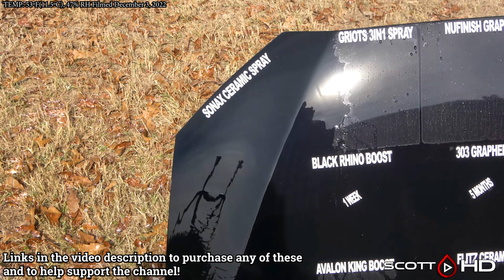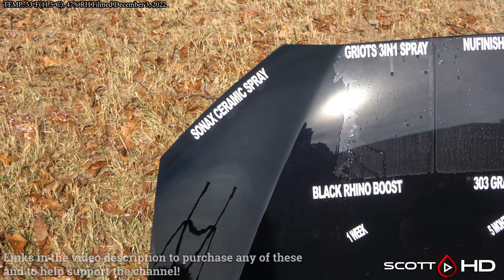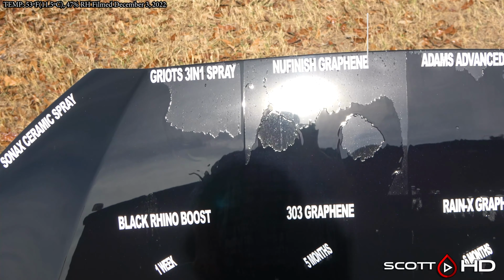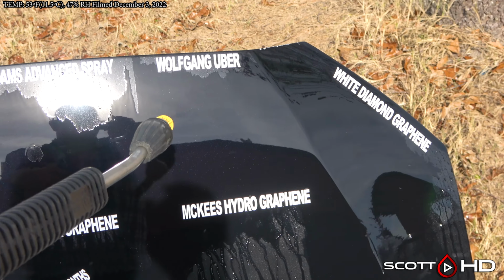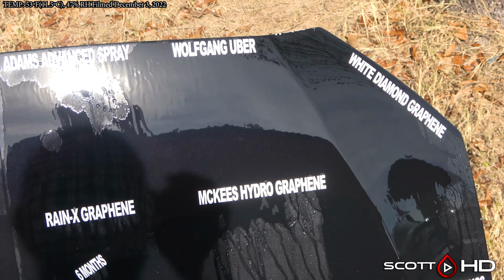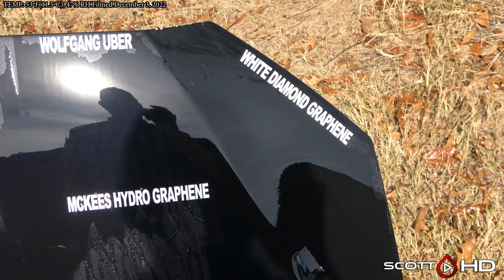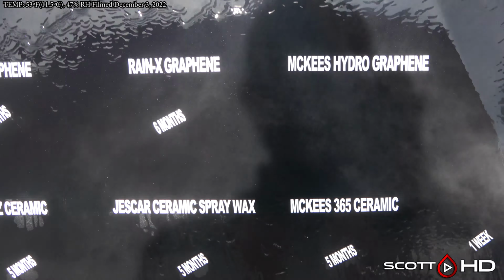So jumping right into it, Sonax ceramic spray, very close to failing. You can see that it sticks for quite a while. Griot's 3-in-1, got some wear on it. Nu Finish graphene, holding up pretty well, but again, it's also got some wear. No surprises or anything at this point. Adam's Advanced and Wolfgang Uber. Wolfgang is very close. White Diamond. We'll give it a pass, but it's really close.